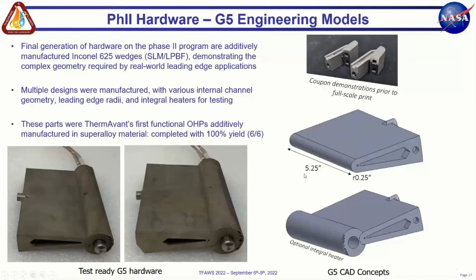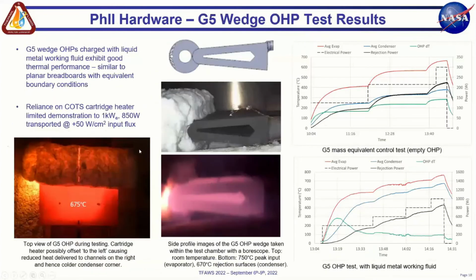So these were additively manufactured and tested successfully. The operation was similar, with the same liquid metal working fluid, to the planar breadboard geometries of the same scale. Here we're again using cartridge heaters to drive heat into this tangent point where the working fluid sweeps through the envelope, driving the heat right into that tip of the working fluid space.